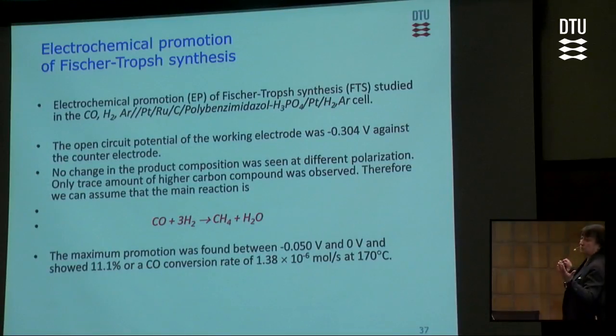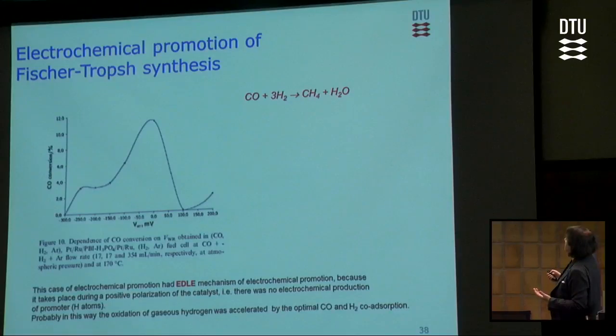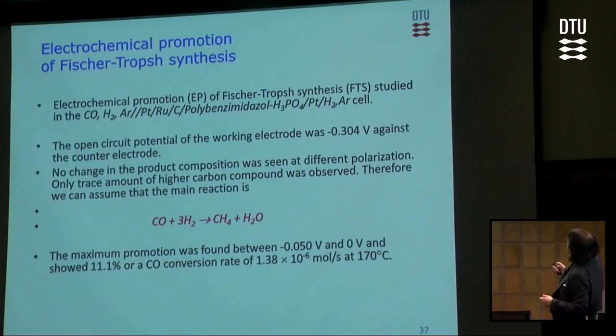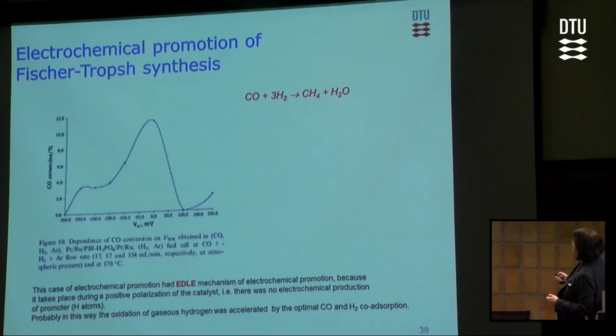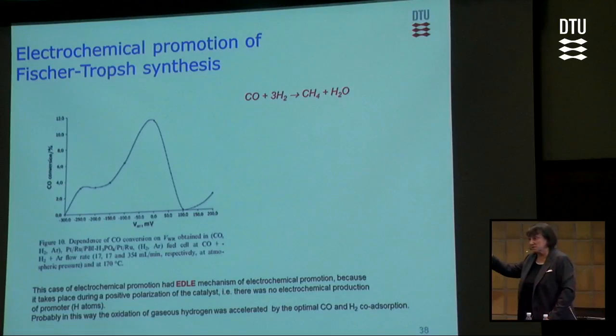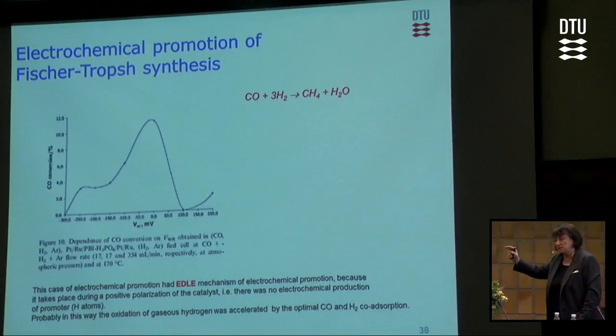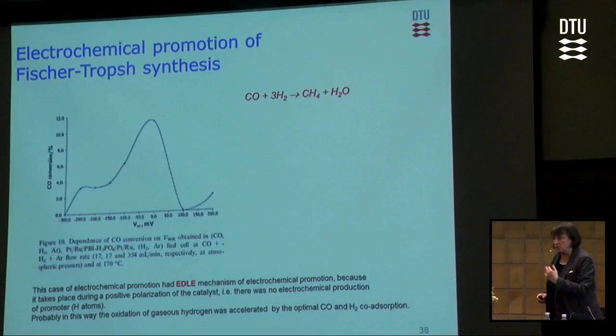And so I'm very proud because that's the Fischer-Tropsch reaction on this catalyst, platinum ruthenium, because this is CO. Look at the temperature, 170. Look at the yield of methane. If you ever read how high the yield was at 600 degrees in an SOFC system, it was around 2%, even less. That's because hydrocarbons are more stable at low temperatures.